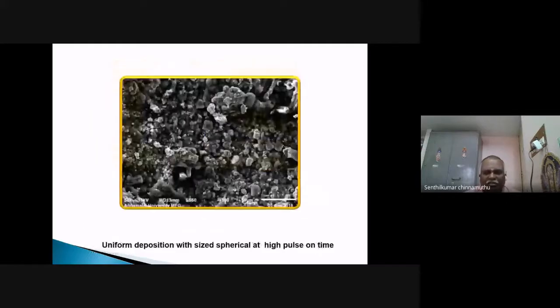See, the figure shows the same morphology of this. Higher pulse on time shows uniform deposition with uniformly sized spherical particles deposited on the surface. At higher pulse on time, more amount of material is melted, and again it is deposited as uniform spherical-sized particles on the surface.